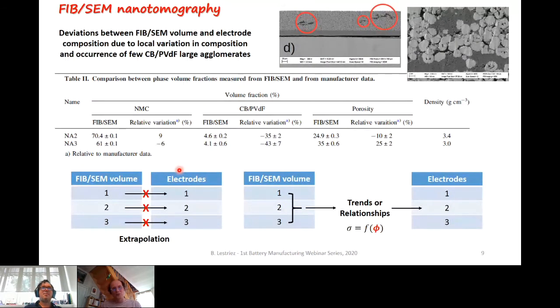So when you speak about FIB-SEM nanotomography and the size of the volume that has been looked at, you must discuss the representativity. And indeed, what we found is that there are deviations between the FIB-SEM volume and the electrode compositions, which is nearly 100% sure due to local variation in the composition of the electrode and not due to a problem of precision, because the voxel size of our FIB-SEM nanotomography is 10 nanometers. That is to say, lower than the size of all objects of interest. It is known, for example, that the smallest features, the nanopores in the CB-PVDF domains, are larger than 20 nanometers.